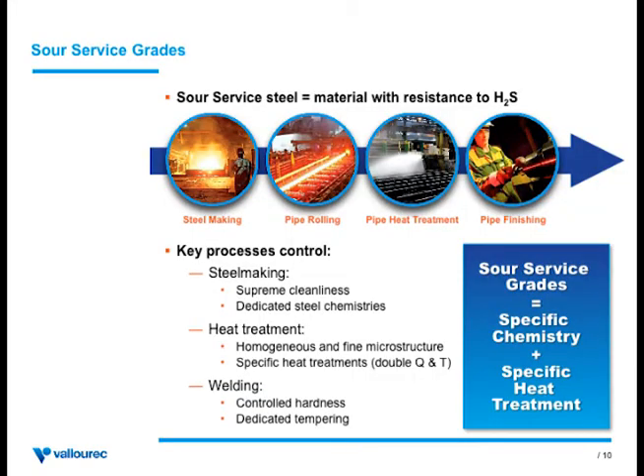What is a sour service grade? Basically, it's the combination of a specific chemistry and a specific heat treatment process. So we have also a lot of additional controls to be done during the steel making operations. This, what we call the steel cleanliness, which is the level of inclusion, the size of the inclusion in the material, matters. If the steel is very clean, there is a lower risk of having a crack initiation in that particular area around the inclusions.